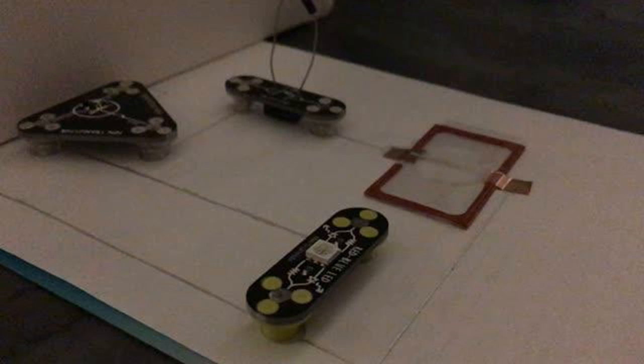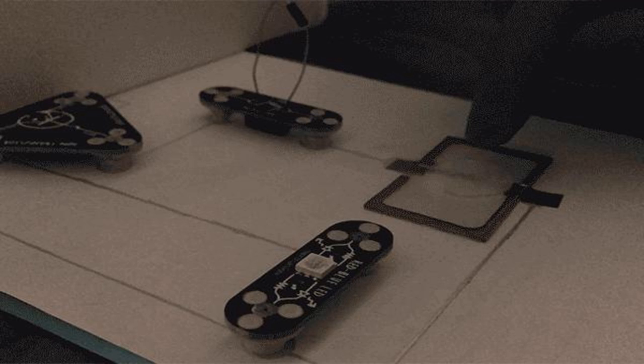This approach is inspired by nature, and because nature doesn't do this on its own, we've manipulated nature to do it for us." To show how their system could be used to manufacture working devices, the researchers used these hybrid organic-inorganic structures as pressure sensors. Identical arrays of domes were grown on 2 substrate surfaces. The 2 substrates were then sandwiched together so that each dome was positioned directly across from its counterpart on the other substrate. Each dome was then connected to an LED light bulb through copper wiring. When pressure was applied to the sandwich, the domes pressed into one another, causing a deformation resulting in an increase in its conductivity. This, in turn, caused the corresponding LED light bulbs to brighten a certain amount depending on the amount of pressure being applied.